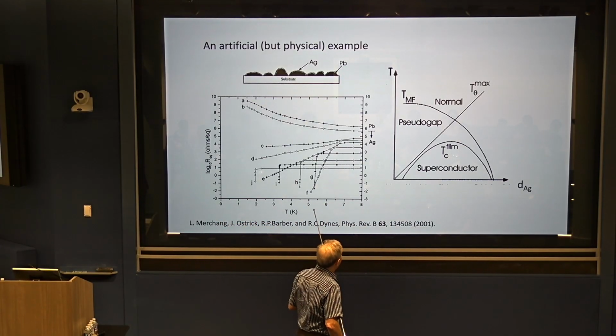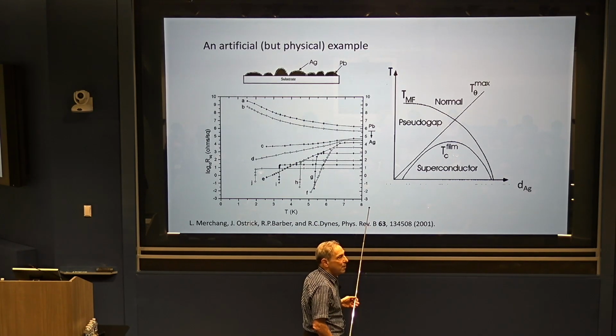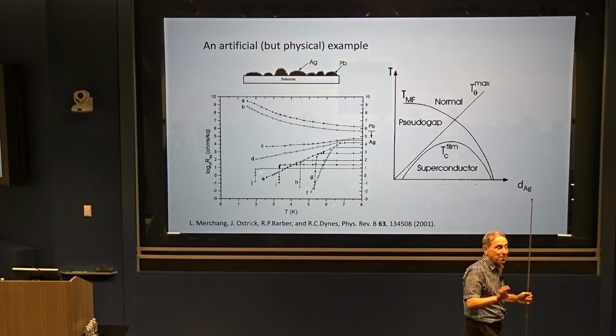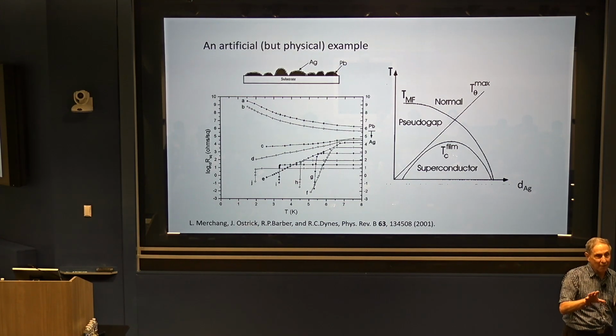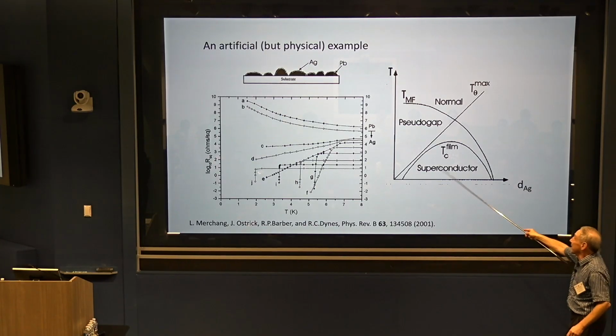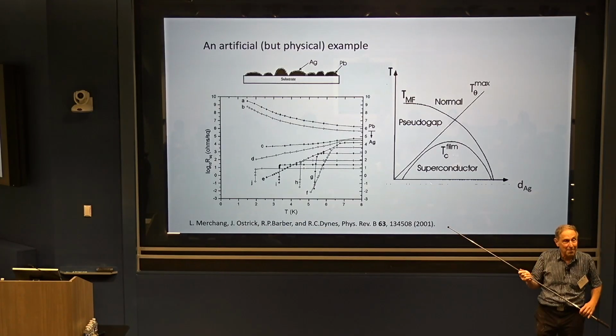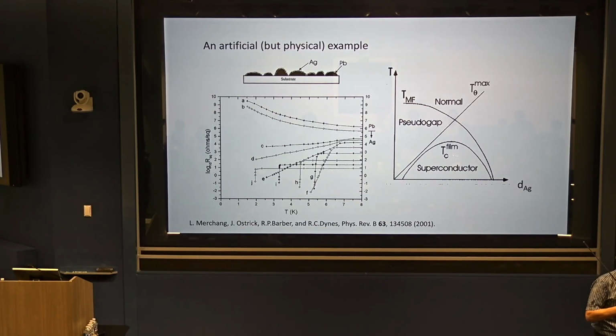But then in the one you described earlier, we would describe that as mixed phase. You have superconducting lead, and then you have silver on top. No, mixed phase means macroscopic mixture of two phases. To me, thermodynamically, mixed phase is like when you have phase separation, you have macroscopic things. These are not macroscopic. This is 50 angstroms. That's a microscopic length scale. So in your schematic of blocks, you're again having an inherent 50 angstrom concept. Yeah, because at a certain point it becomes mixed phase, and it's just a question of what size you're talking about. Correct. Okay, I just wanted to understand. Very good, thank you.